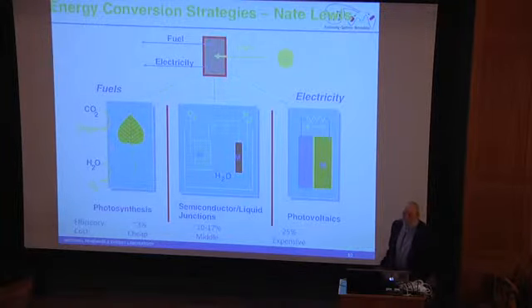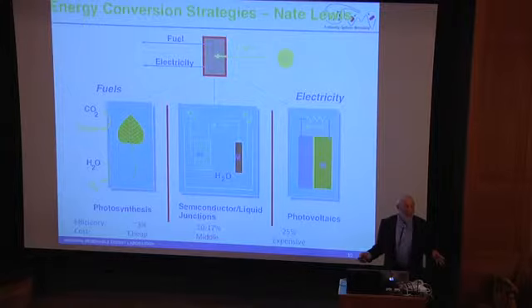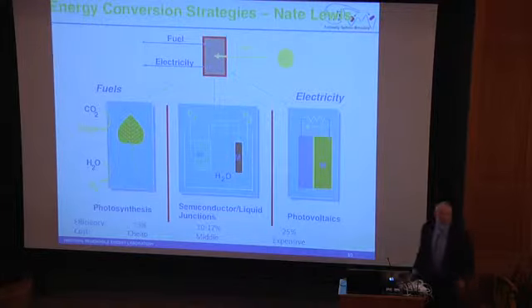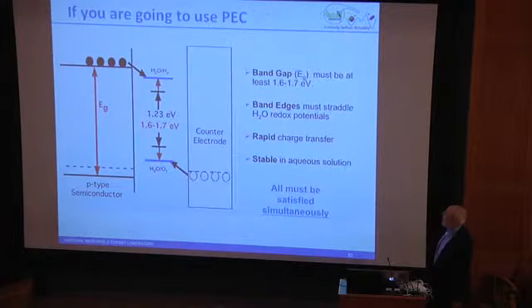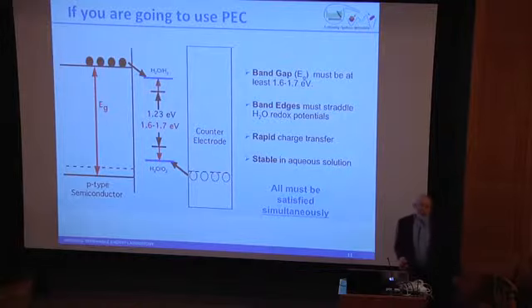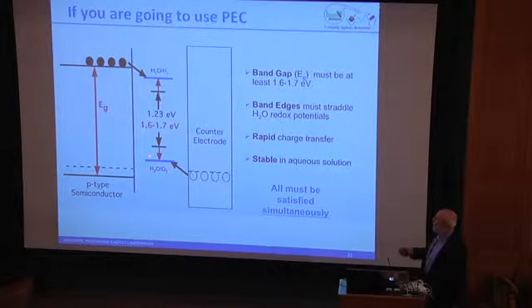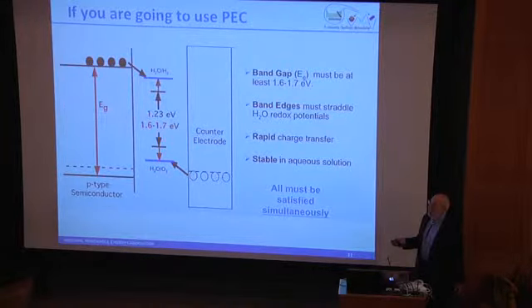And whether you believe in it or not, it's a really interesting science challenge because it combines semiconductor photoconversion with electrochemistry in a way that is very useful for us to understand. So the energetics are what really are the problem. You have a counter electrode, you have your semiconductor, you have some kind of band bending, you have a band gap. And the problem is that although the water couple is only about 1.23 volts to get oxygen and hydrogen, in reality there are overpotentials on both sides that drive the needed potential to around 1.6 to 1.7 volts